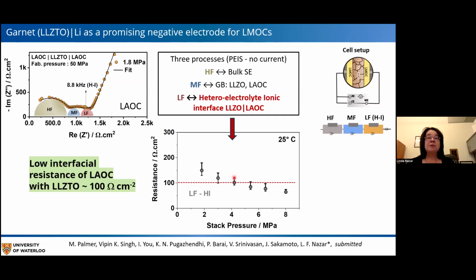And when we do this as a function of stack pressure, you can see that we're able to achieve resistances of less than 100 ohm centimeter squared over very, very low stack pressures. So we think this is rather exciting as well.